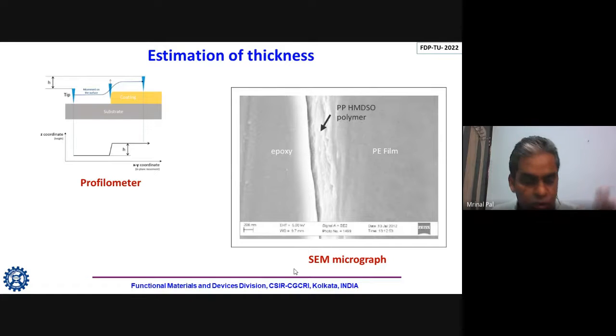So by using a scanning electron microscope also, you can measure the thickness of your film, and also you can measure the thickness of the interfacial region, which is not possible using this profilometer. The profilometer can just measure the thickness of your film, but not the interface thickness. But if you use a high resolution scanning electron micrograph, then it's very easy to measure the thickness of the film and also the thickness of your interface.